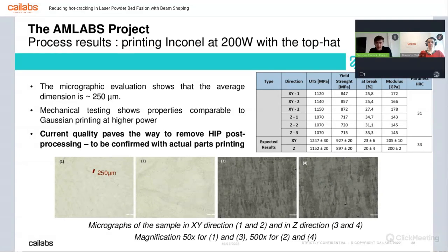And then we have compared the result that we have obtained with the expected one, while for the expected one are the result that we have observed printing Inconel 939 on your machine. In general, what we have observed is a decrease in mechanical properties of roughly 100 megapascal, that it's not that much considering that this part needs to be heat treated at the end.